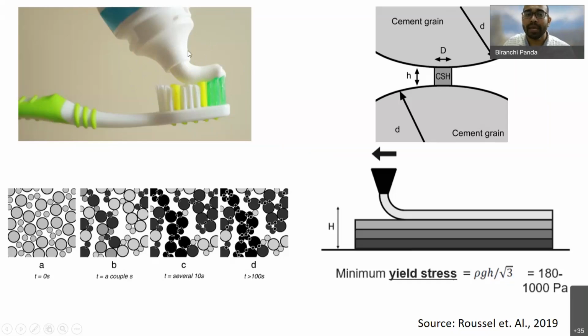What is thixotropy? It means once you apply a high shear rate, the material should easily come out of the nozzle, but as soon as you remove the force, or stop pressing the tube, it should remain in its original position. So that is the unique feature of thixotropy, and we need a similar material property in the concrete printing process. As I mentioned here, the minimum yield stress is around 1000 Pascal. If you maintain this kind of yield stress, we can deposit the layer smoothly without any deformation.